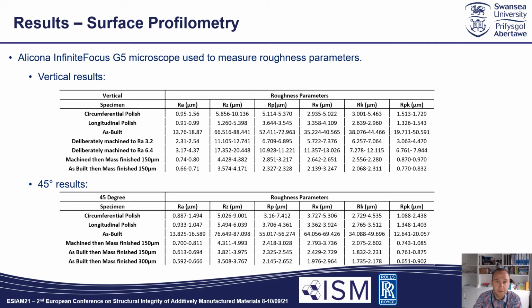For these though, the Rp value, or the maximum profile peak, has more of an established ordering, with the longitudinal finish the worst, followed by the circumferential polish, and then the 3 different mass finishing conditions, with the highest micron finish, as expected, having the most optimal finish.